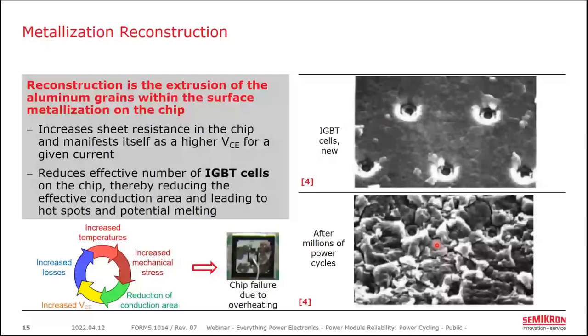And so that extrusion here increases the electrical resistance laterally across the metallization, and it also reduces the functional area of the IGBT chip as these individual cells get distorted. Less IGBT area means higher conduction losses and higher temperatures driving more reconstruction. Again, a cyclical process that results in overheating on the chip itself.